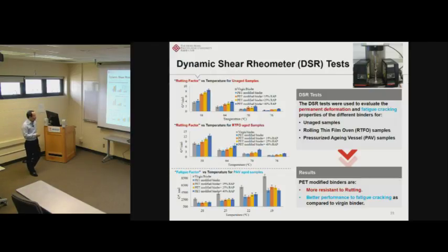And at the bottom, we can see the test results for the fatigue factor. For the fatigue factor, contrary to the rutting factor, we want a relatively lower value, because to have better fatigue performance, we want the material to not be that stiff, to have good fatigue resistance. So a lower fatigue value actually represents a better fatigue performance of the binder.